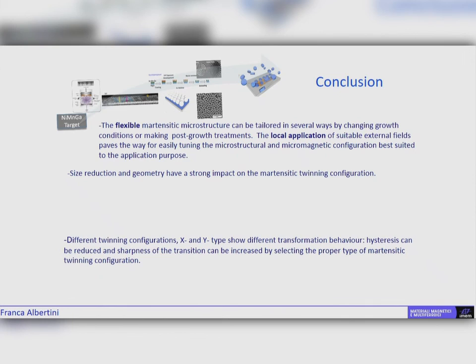So coming to my conclusion, what I wanted to point out is that the flexible Martensitic microstructure can be tailored in several ways, both during growth and after, by the application of magnetic field, of heat treatments, and that the local application of temperature or of stress and of magnetic field is suitable for tuning the microstructure also locally. The size reduction and geometry have a strong impact on the Martensitic twinning configurations, and looking at the Martensitic path, different microstructures have different transformation behaviors, and the hysteresis depends on the kind of microstructure.